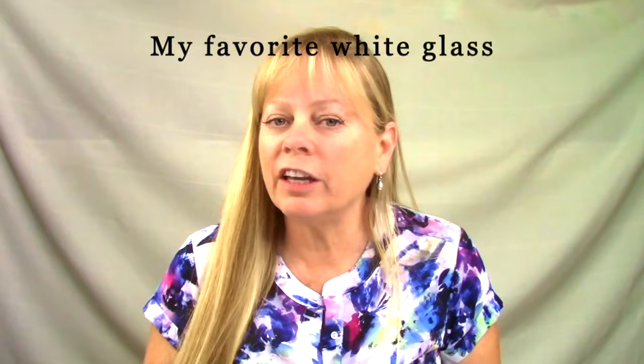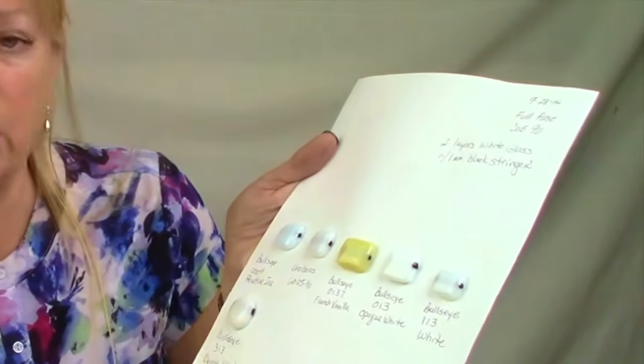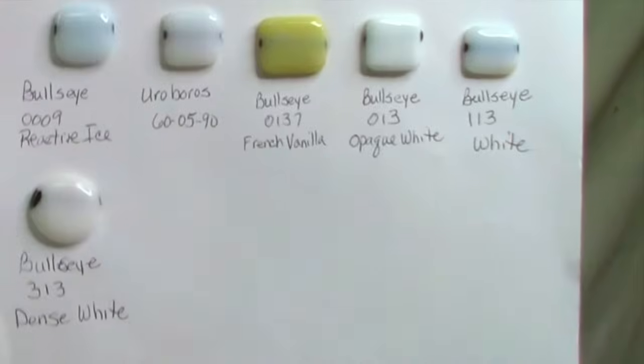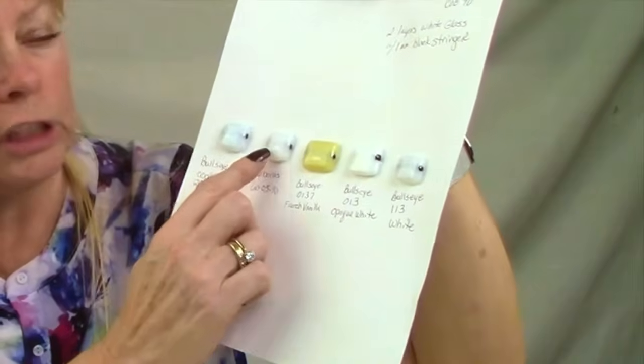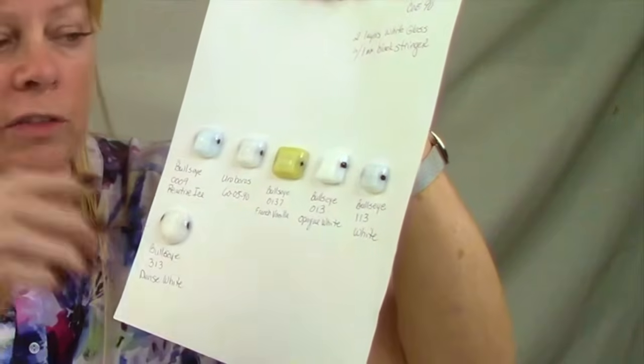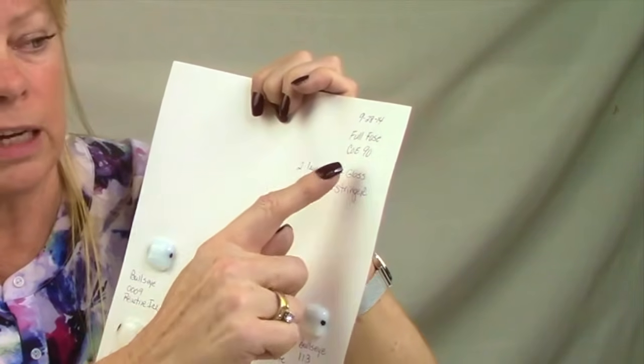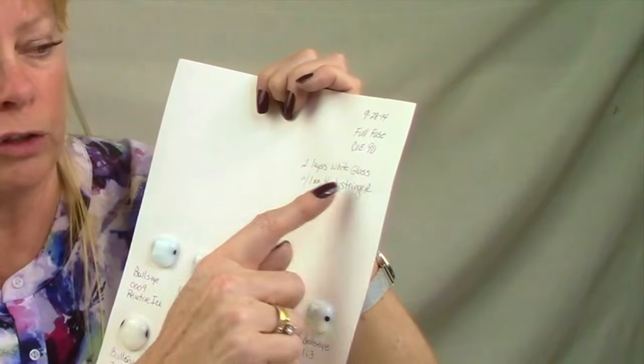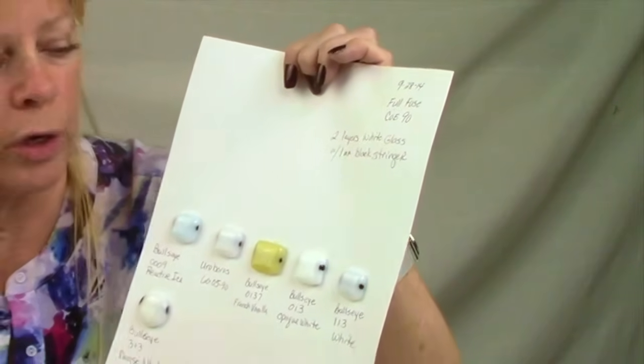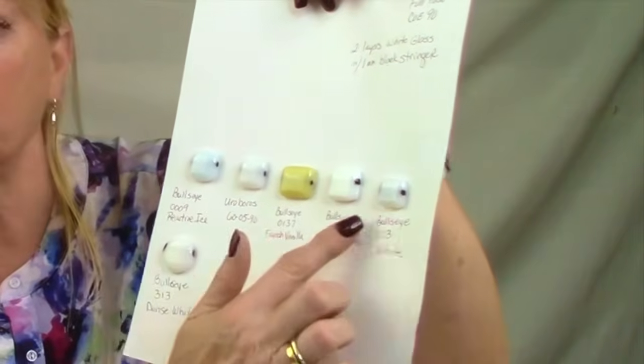By the way, I have a favorite white glass. When I am fusing with COE 90, I'm usually using Bullseye glass, but not always, and I want a white glass. My favorite is 013 white. And the reason is I did a test. I tested Bullseye glass and Uroboros glass and keep this in a binder. I put a little black stringer between 2 layers of glass, and I documented the date I did it, the full fuse COE 90, 2 layers of white glass with a 1 millimeter black stringer in between. And then I kept track of which colors they were.